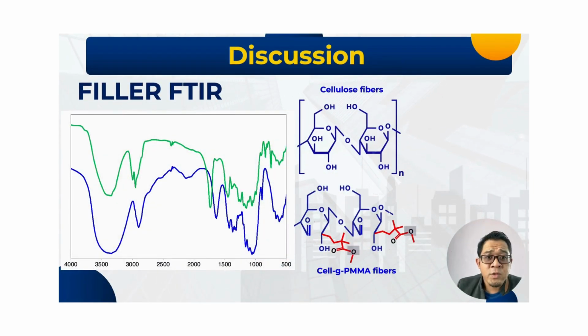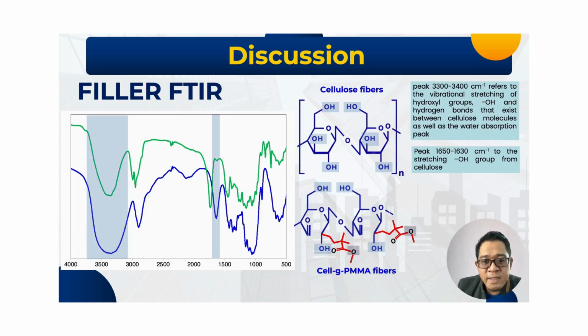Next, we go through the discussion. See the peak at 3,300 to 3,400 per centimeter, which refers to the vibrational stretching of the hydroxyl group OH and hydrogen bonds that exist between cellulose molecules, as well as water absorption peaks, and peaks around 1,650 to 1,630 per centimeter refer to stretching of the OH group from the cellulose.